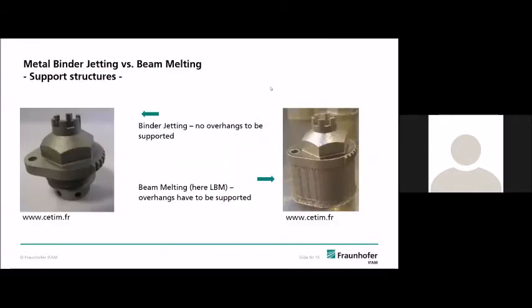And one big difference between the metal binder jetting approach and the beam melting approaches is that with metal binder jetting, we need no support structures during printing. So overhangs do not have to be supported, and the pictures on the right, these two pictures represent the same part. On the left, the binder jetting approach, and on the right, the beam-based approach, which has to be supported. That's the big advantage of binder jetting compared to the beam-based processes. So no contact to a build platform, no support structures.